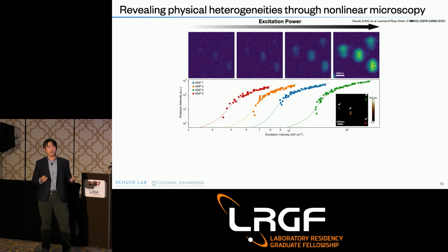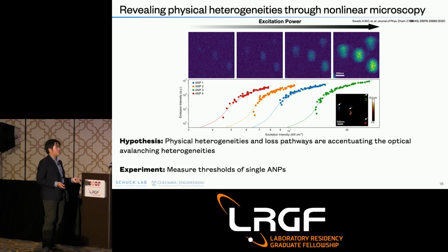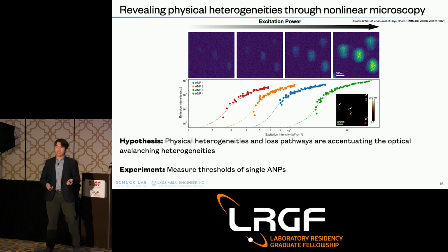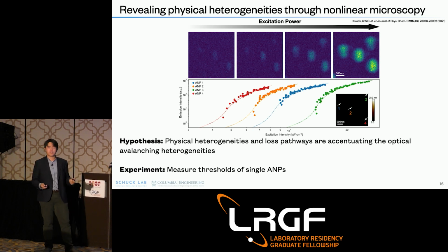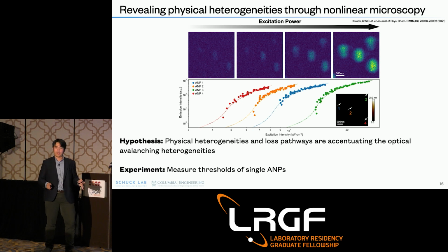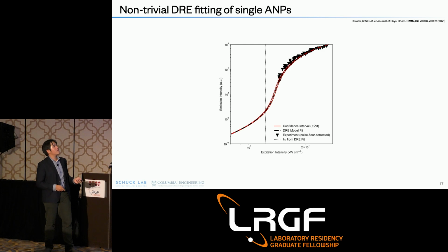the fact that they do not all turn on at the same time. Additionally, when you look at the S-curves, not all of them avalanche at the same time either. One of the hypotheses I was forming was that the physical heterogeneities and the loss pathways are being accentuated by the avalanching effect. And the experiment is to measure about 300 plus single ANPs to build up a relationship for this hypothesis.